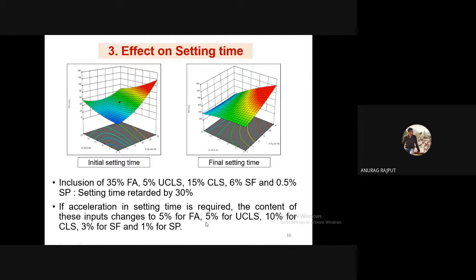If we talk about setting time, it is increased with the inclusion of these dosages: 35% of fly ash, 5% of uncalcined limestone, 15% of calcined limestone, 6% of silica fume, and 0.5% of super plasticizer lead to the retardation of the setting time by about 30% as compared to the control mortar. And for the areas where we need acceleration in the setting time, where we want our mortar to set quickly, then these are the dosages of these input variables.